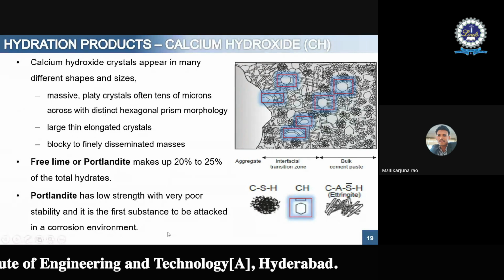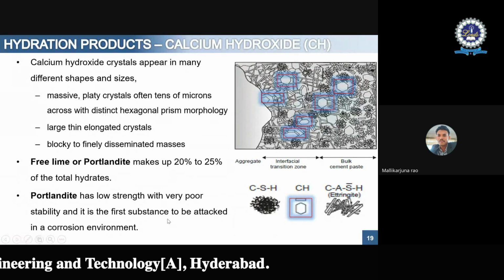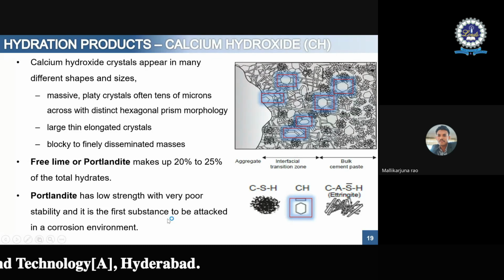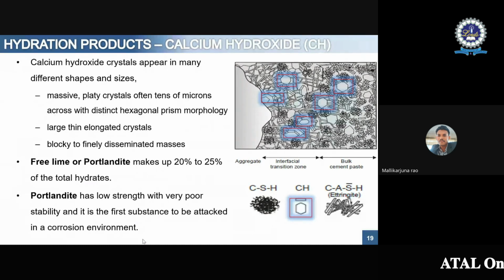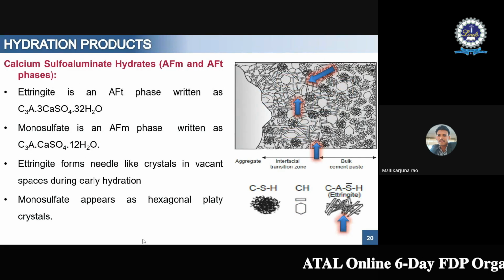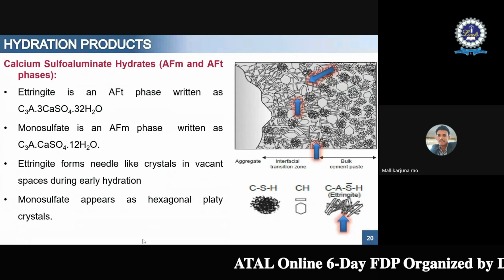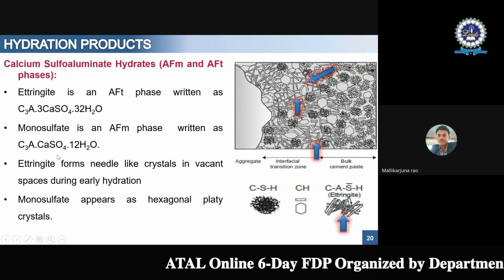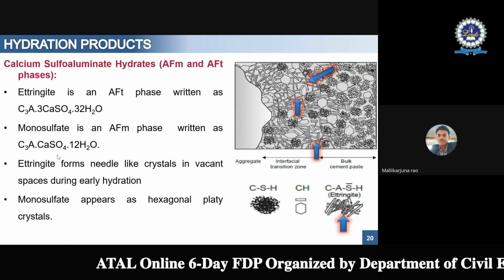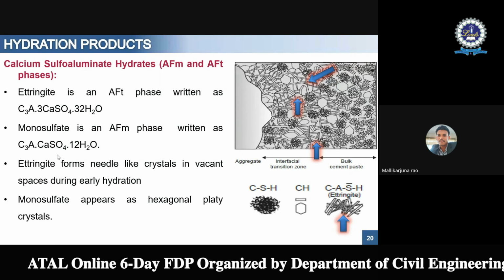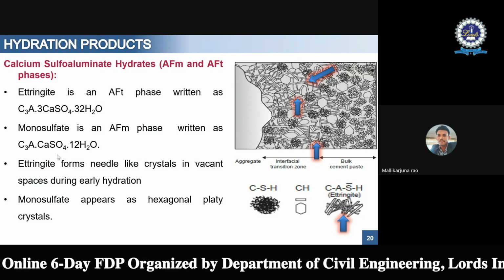This free lime volume is approximately 20 to 25%, where the portlandite contributes less strength. Once the portlandite is present, it easily reacts with the harmful ingredients present in the environment, and it then leads to corrosion as well. This is nothing but the calcium alumina silicate hydrate, where ettringite formation would be there. The ettringite are crystals where, during early hydration, you had some amount of spaces there. In later stages, because of the densification, it will give you more strength.